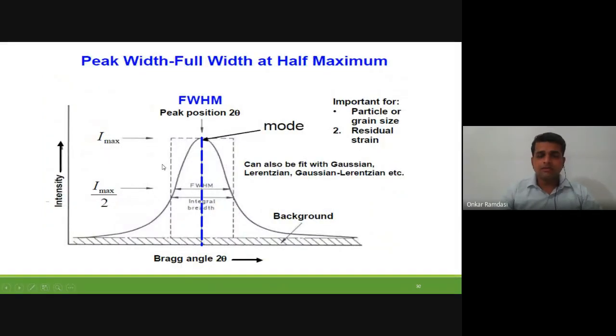Now these are the different parameters which we can calculate. Whenever you take any peak, if you want to calculate the particle size or the residual strain in that material, in this case the strain will be different. It is lattice strain, the one which you use in the elasticity chapter. Full width half maximum: first of all, the intensity is arbitrary. Remember, if you take XRD today and get intensity 1000, and the next day you perform the same sample, at that particular angle your intensity might vary. It will depend upon the atomic position, the temperature factor, the absorption factor. Now whenever you halve the intensity,